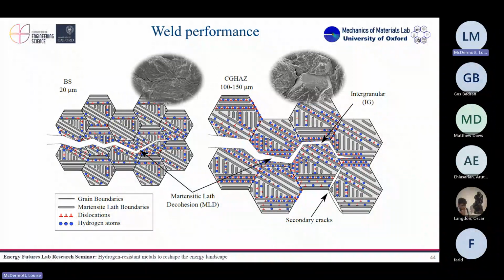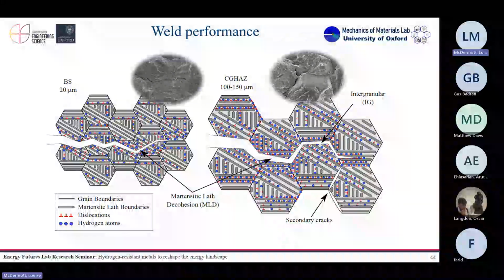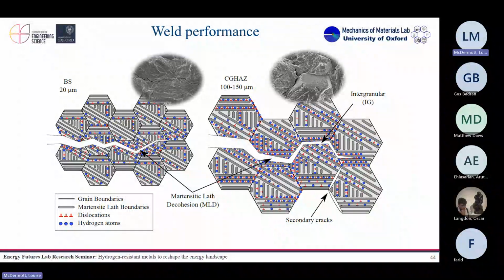That, let's say, the density of hydrogen in those internal interfaces is going to be much lower because you have a lot of internal interfaces. While if you have very, let's say, big grains, so you have less internal interfaces, the amount of hydrogen that you're going to have in those interfaces is going to be greater. Okay? So it's basically density of interfaces.